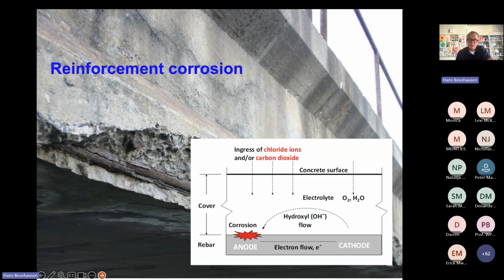And once that happens, you can see in the background here a piece of reinforcing steel that is corroding. Once you have reinforcement corrosion, rust is developing, and the rust is expanding in volume. Again, it's an internal growth in the concrete matrix that can't be accommodated, leading to stresses, cracking, delamination, and spalling. And that is the main problem that we have with aging existing infrastructure all over the world, in fact.